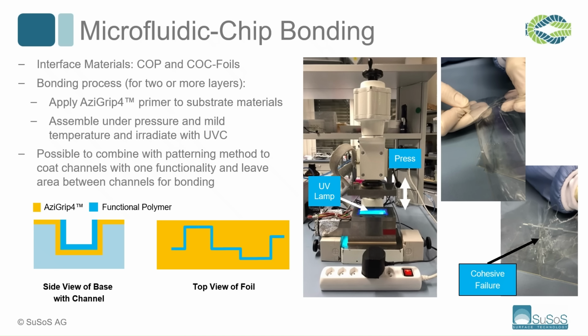Here, the short example of how we can use the Acibond with the AsiGrip group for bonding of two different substrates. It's a polymeric substrate, so COP and COC foils. What we do is we take the foils, we apply the AziGrip4 primer to the substrate materials, then we press both materials together and irradiate it with the UV. And as you can see, upon the heat, upon the UV illumination and upon the pressing, the two materials can bond together. And as you can see here, there is a cohesive failure, so the material rips due to the strength of the bond between the two foils. So there is not a failure in the adhesion layer, but in the material that is far less strong than the glue in between.